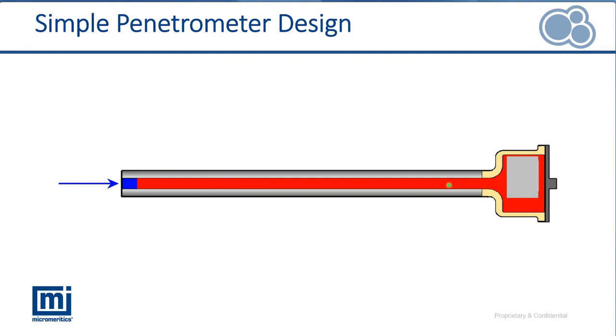We have not really started applying much pressure yet, so we haven't pushed mercury into the pores of it at this point. By the way, if we know the volume of this sample holder when it is empty, and we can determine that by weighing the amount of mercury that it'll hold, if we know the density of the mercury that's in there.